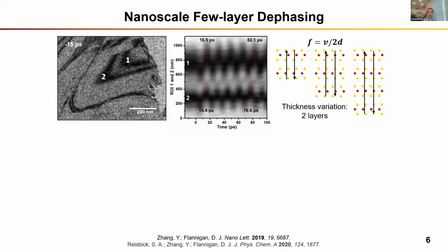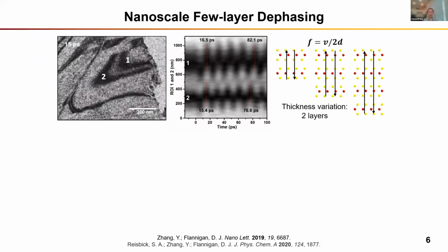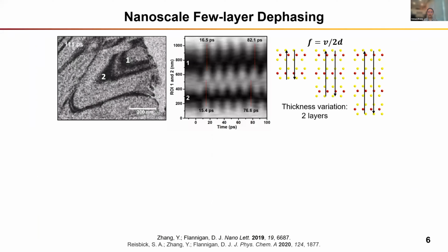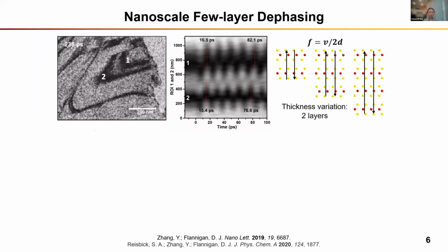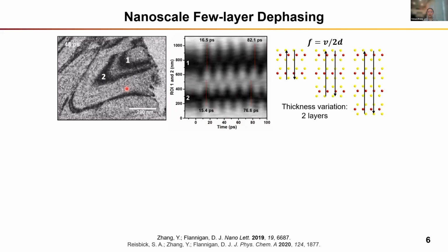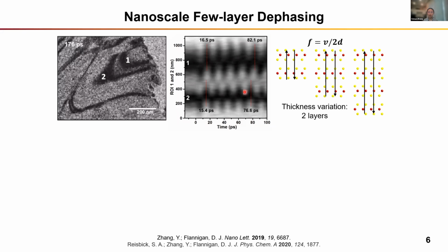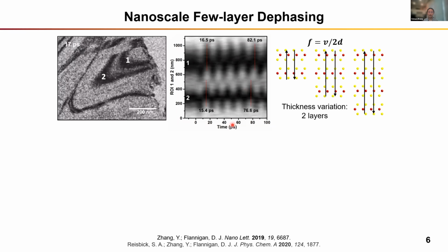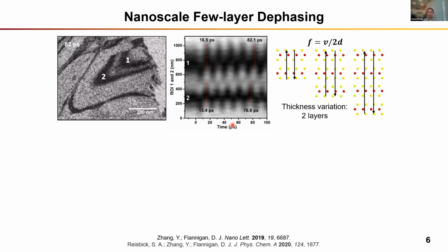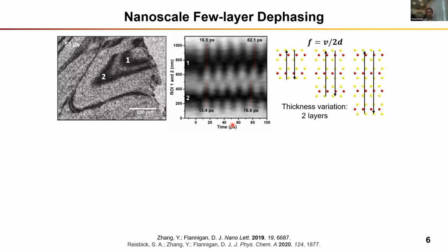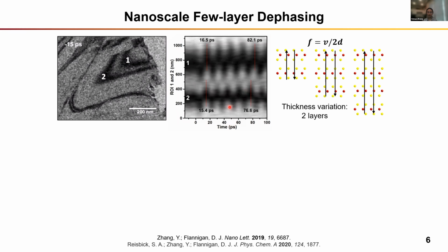Let's take a closer look at this tilted region. If we watch carefully, we can see a dephasing phenomenon of these two bend contours. And this is perhaps more obvious when we plot the position of the two bend contours as a function of time, and we call this a space-time contour plot. The red lines here label four oscillation periods of both bend contours, but the duration is quite different. And this is due to a very small difference in the thickness.